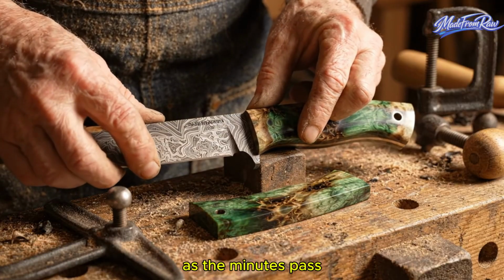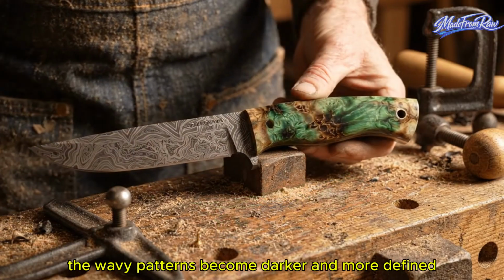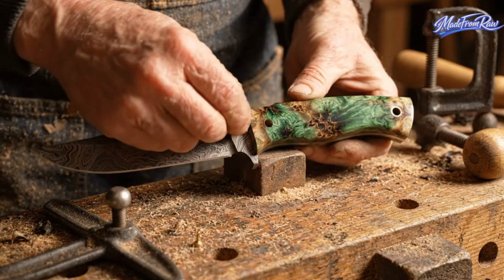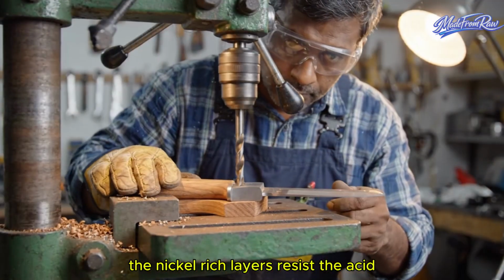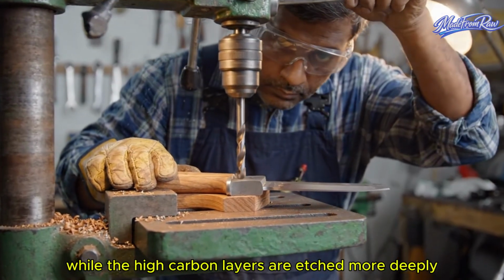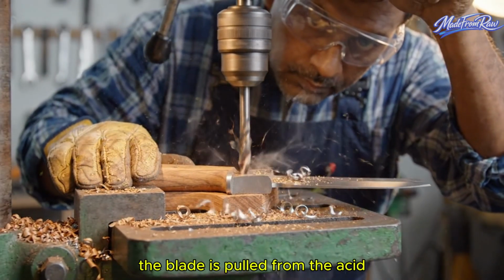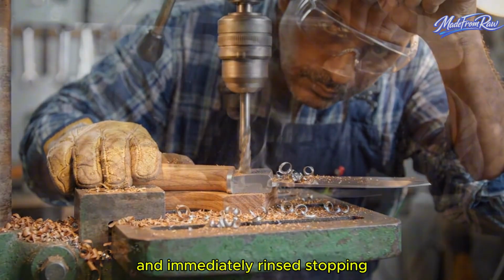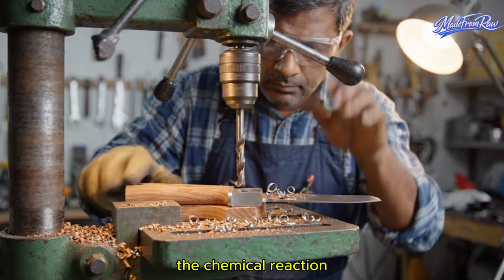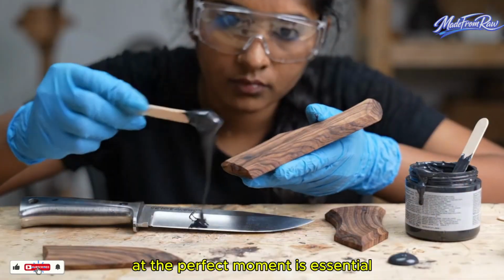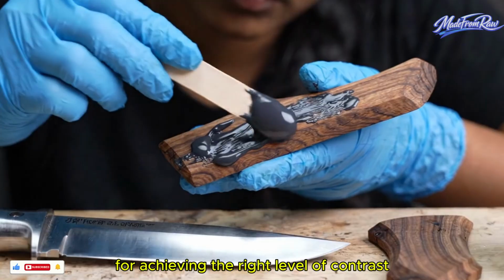As the minutes pass, the wavy patterns become darker and more defined. The nickel-rich layers resist the acid, while the high-carbon layers are etched more deeply. The blade is pulled from the acid and immediately rinsed. Stopping the chemical reaction at the perfect moment is essential for achieving the right level of contrast.